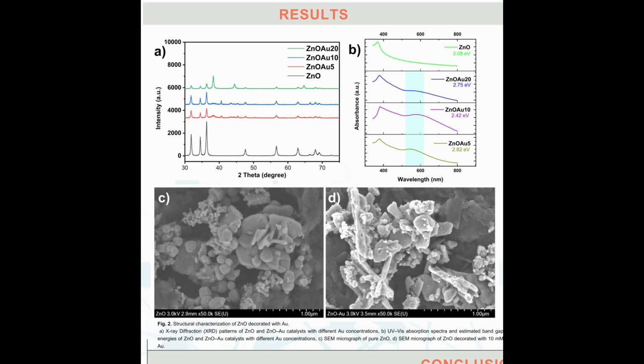Morphological analysis. Scanning electron microscopy showed granular zinc oxide with high surface roughness. At 5 and 10 millimolar gold, nanoparticles were well dispersed, creating numerous metal semiconductor junctions. At 20 millimolar, larger agglomerates formed, potentially blocking active sites, despite increasing the total electrochemically active surface area. Ultraviolet visible spectra revealed the gold surface plasmon resonance band in decorated samples, absent in pure zinc oxide. Band intensity grew with gold content, indicating more nanoparticles on the surface.